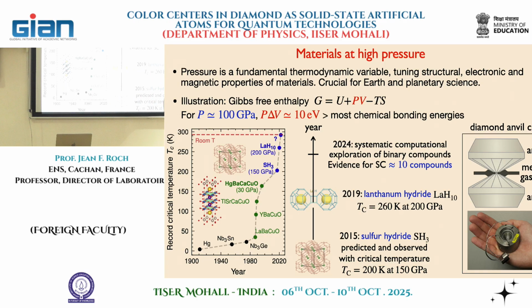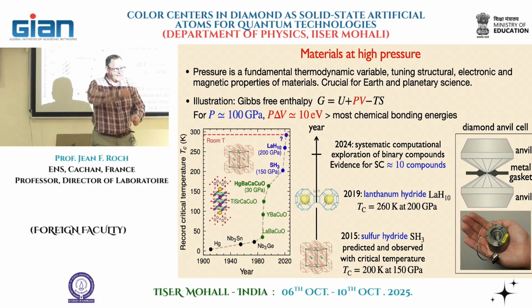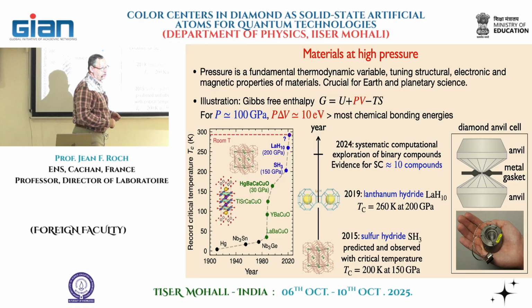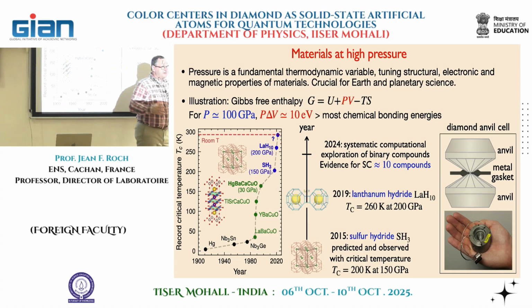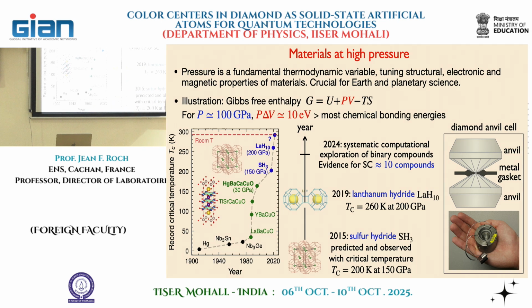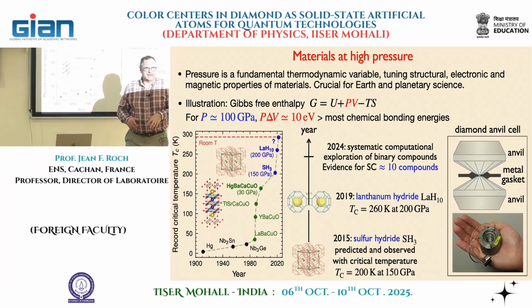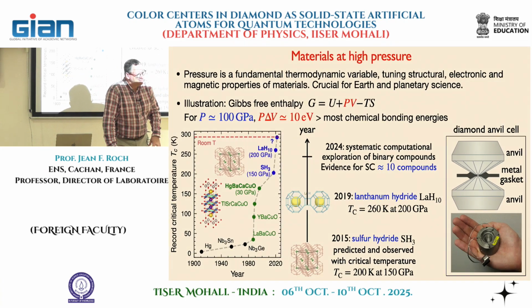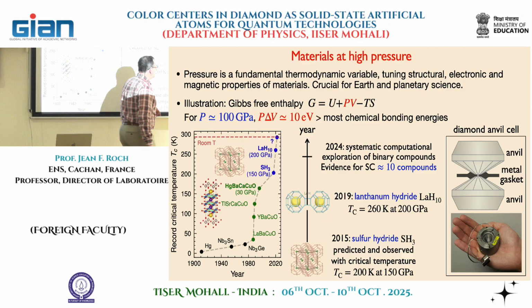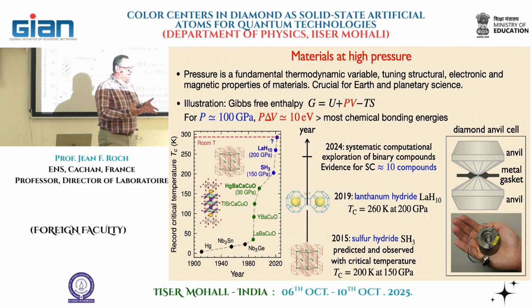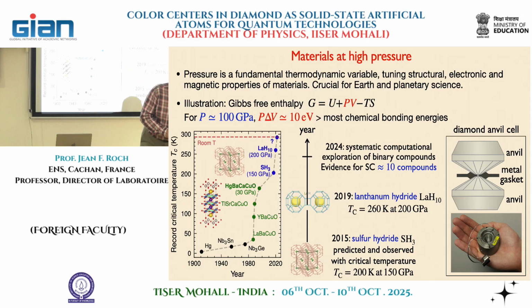So the two anvils, we squeeze them against each other. And inside, there will be a pressure transmitting medium. The material will be embedded, and that will be used to apply hydrostatic pressure onto the sample itself. And there is also a lateral confinement that is ensured by a metallic gasket. It is done, for instance, in rhenium, the metal that has the highest stiffness. You drill a hole in this metallic gasket, and this is squeezed with everything inside, and at the end, you have this system. And what's remarkable is that at the end, it's like a bottle. You can imagine my bottle here. I have these two tips like that, the gasket in between, but now I can take it in my hand, and I can go wherever I want. I could have brought it here.